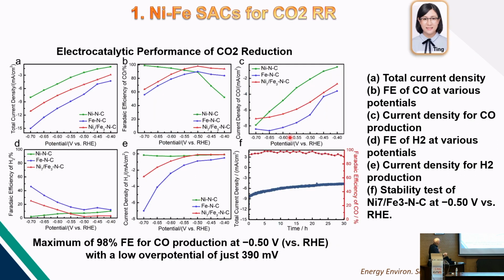So then you can just go to the electrocatalytic performance of the sample. You measure the different samples with nickel alone, iron alone, or the combination of both, and you see that the combination is always performing better at the voltages that you wanted. So the stability is even much better in the case of using this combination of two. So this was just an example.